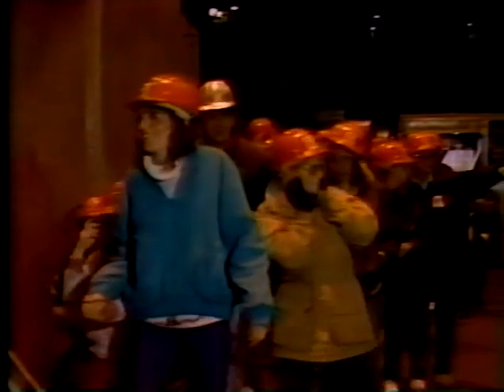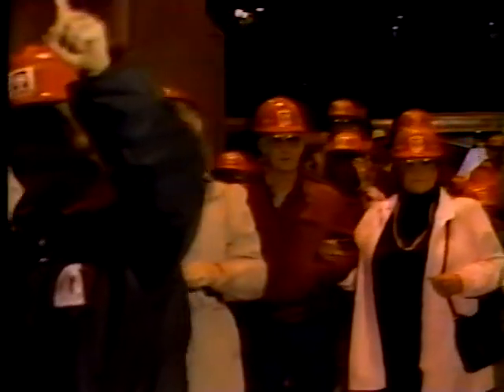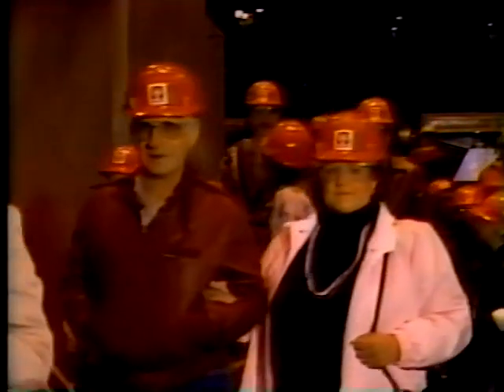No, we don't dip coils in vinegar and salt to pickle them. Rather, we wash the steel and treat it with hydrochloric acid, which removes any scale and lightly etches the surface of the steel. This operation takes place within the 240-foot tower that dominates the skyline of the plant. At the end of the pickle line, the continuous strip of cleaned, etched steel is cut to specific lengths and recoiled, only to be uncoiled again for its trip through the four-stand tandem mill.